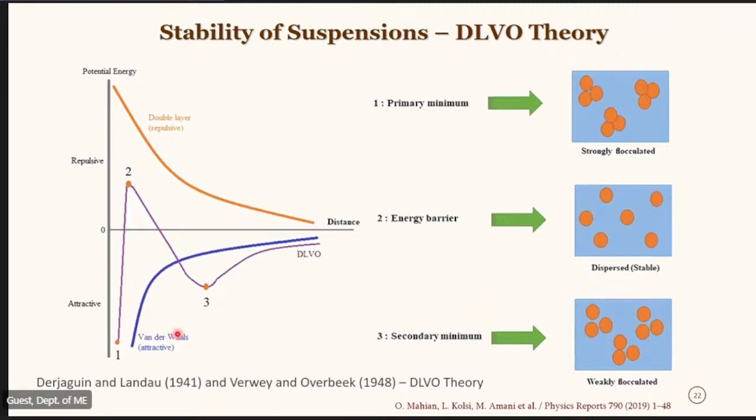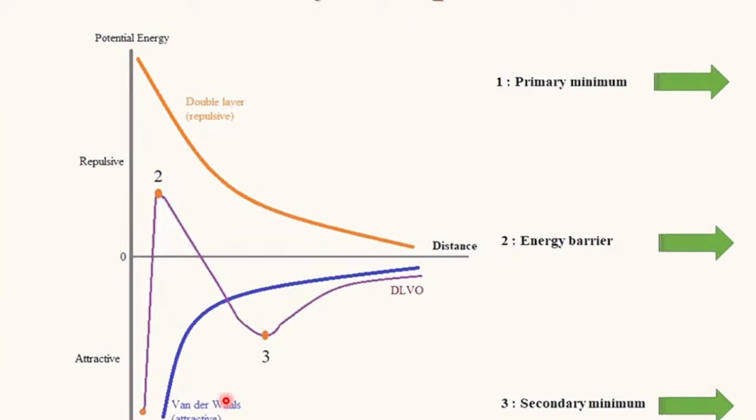And if it has a surfactant, which creates a repulsive barrier between one particle and another, once the van der Waals forces of attraction are overcome by this steric effect, the two particles stay separated and are not going to collide or get attached to each other. This makes the particles stay there for a long period of time.